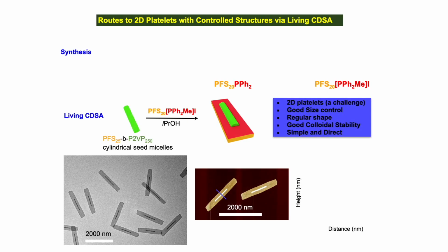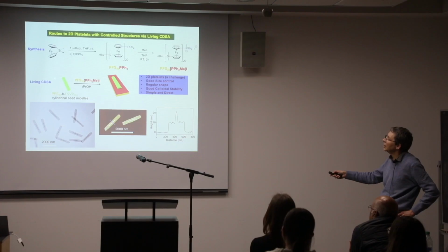So again, when we started this work, we used this polymer with the two methyl groups on silicon, which will crystallize, and this is our charged group, a phosphonium group at the end. And then what we do is we make 1D seeds by living CDSA, and then we add this polymer to them. When this adds, it crystallizes off of the ends and then surrounds the seed, and you get a 2D structure like this.